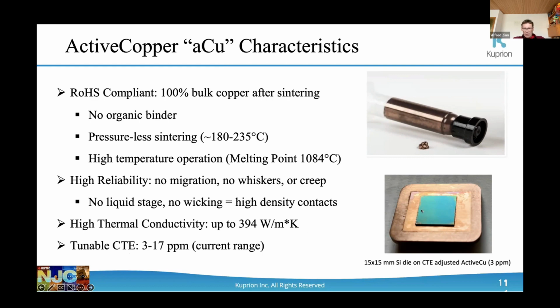So here's actually an example that we just recently did. This is a 15 by 15 millimeter silicon die on our CTE adjusted copper. You try that on normal copper, I doubt you'll even be able to stick it because it will pop off when you start cooling down. It comes out of the oven due to the high thermomechanical stresses that you have between the two.